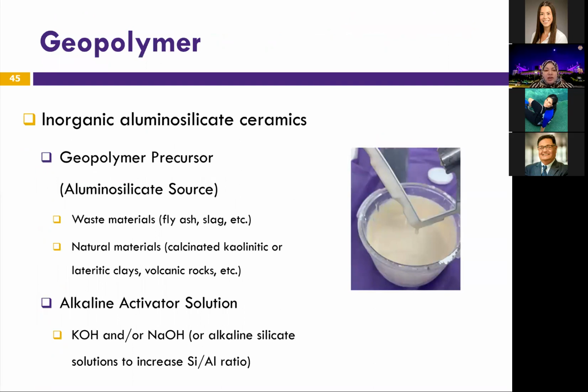You start with a geopolymer precursor and an activator solution. The geopolymer precursor is an aluminosilicate solution, and it can come from waste material like fly ash, slag, etc., or from natural materials like calcined kaolinite. One example of that is the metakaolin that we used in this project. The alkaline activator solution can be sodium-based or potassium-based, and we sometimes add to it alkaline silicate solution to increase the silica-alumina ratio.